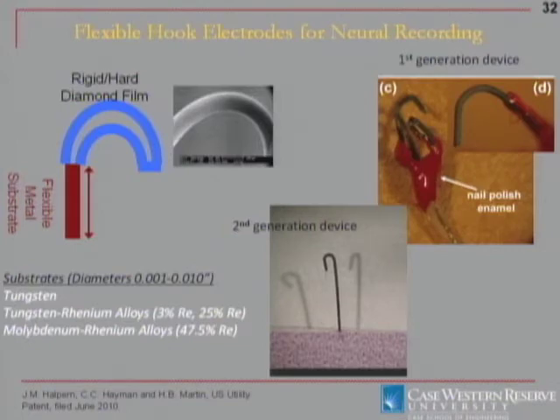So the first method of putting diamond on a high temperature material that remains ductile, this goes back to the idea that those tungsten micro wires that we were growing on, those discs, in order to get good adhesion to that, there's a carbide layer that forms, and that carbide layer becomes very brittle. And for large electrodes, you can pretty well snap your electrode just by dropping it by 2 feet from a desk. If you drop it properly, you will break the electrode. And it's not because the diamond isn't hard, it's just because that substrate underneath has gotten to be so brittle.